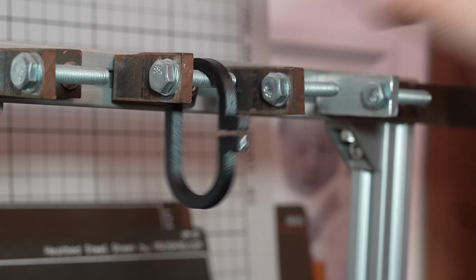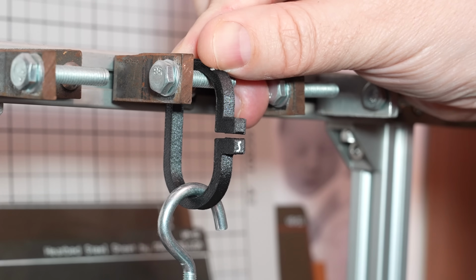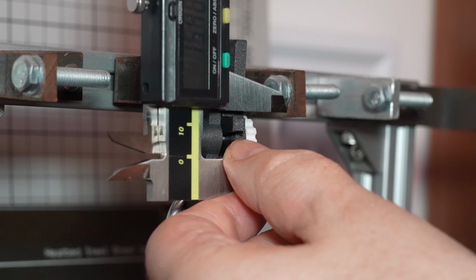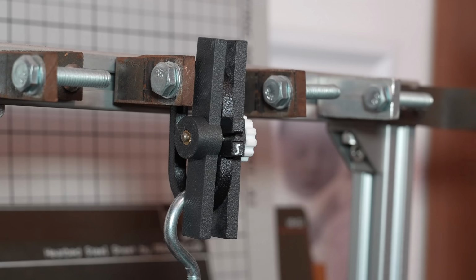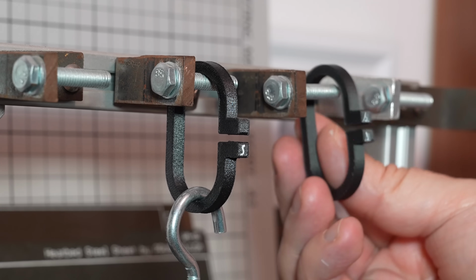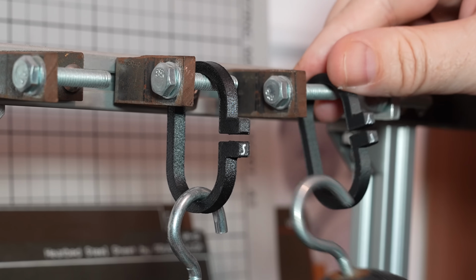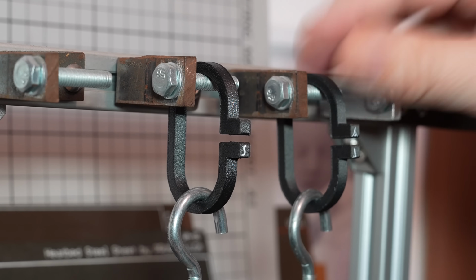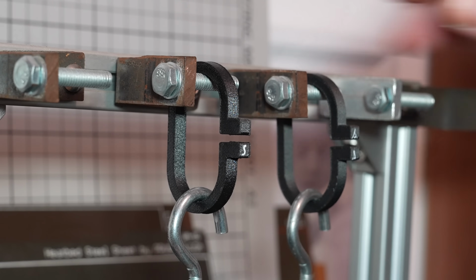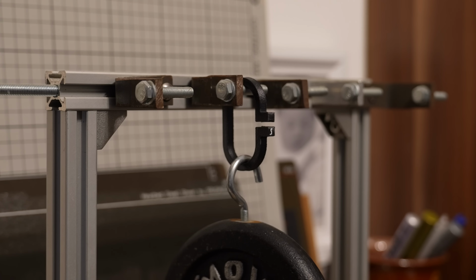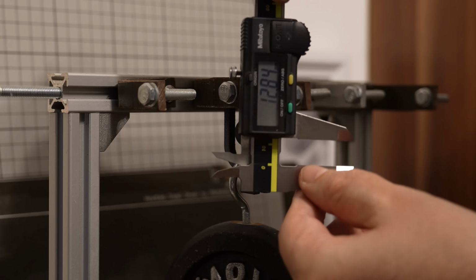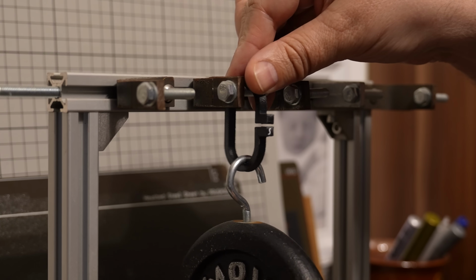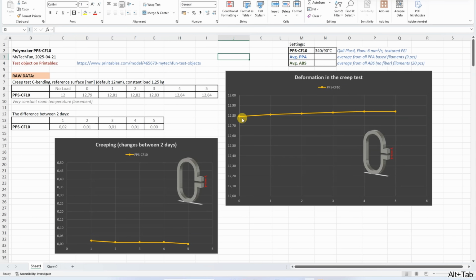The creep test of deformation under constant load of 1.25 kilograms. 12.79. For the first look, the deformation looks very similar to PPA. I already did the test with this one, just side by side shortly to show you. As you can see, very similar deformation. And the last fifth day, 12.84. This deformation is slightly bigger compared to the average PPA, but far less than average ABS. But the creeping that changed during the time is almost zero, exactly like with the PPA materials.